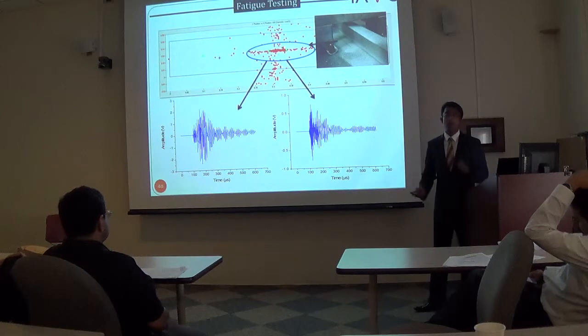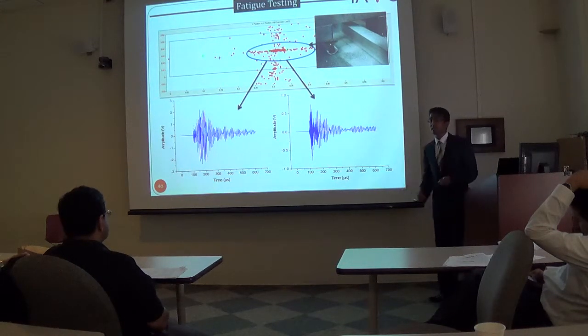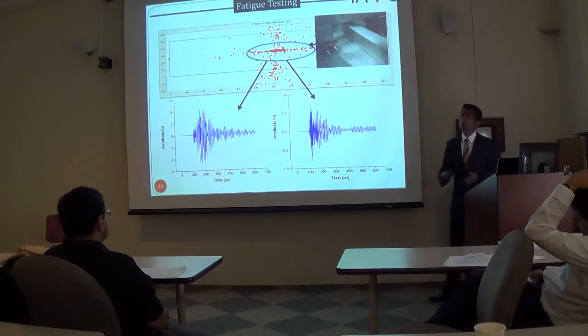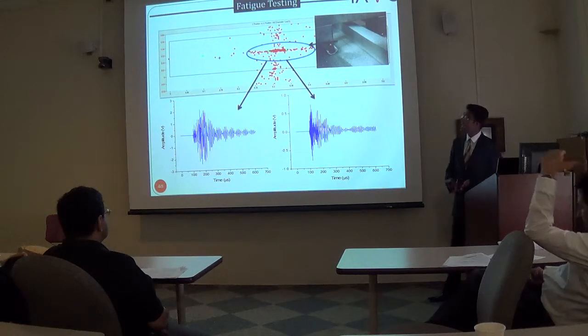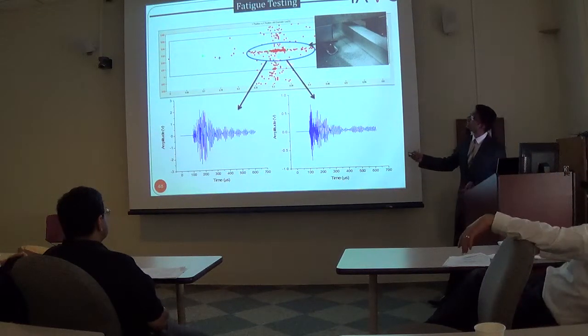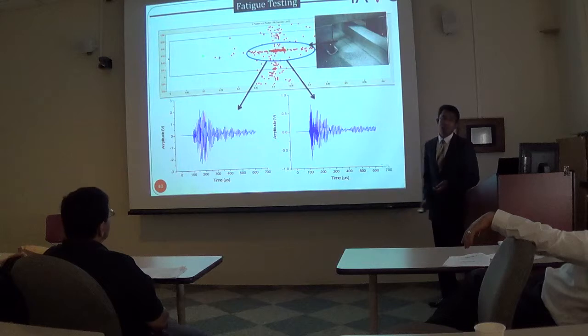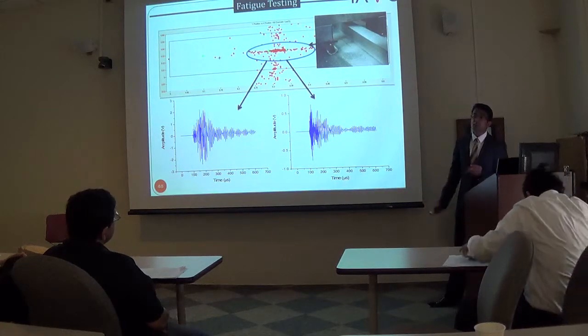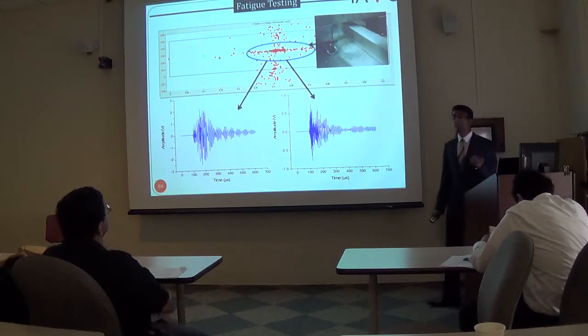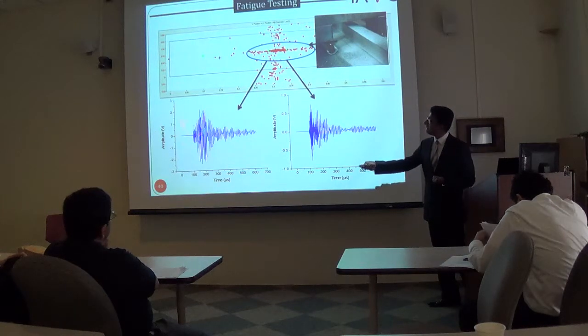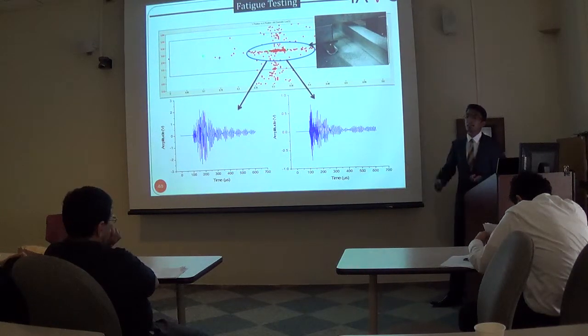region of debonding, but also, more importantly, to spatially filter the large AE waveforms that were collected during the fatigue testing of the material. And you can see that the AE waveforms collected from this location seem to be very similar to the AE waveforms that were picked up from the tensile test. You can see that the initial waves are associated with the high frequencies, and subsequently they're associated with the low